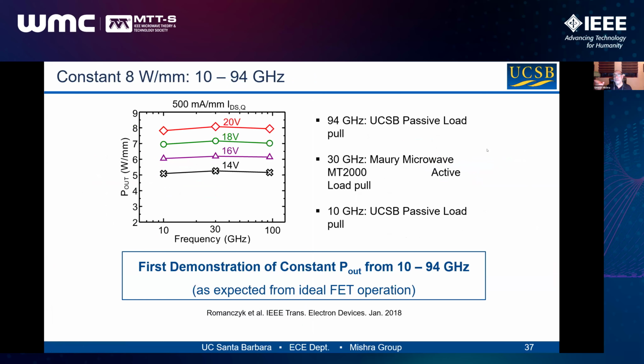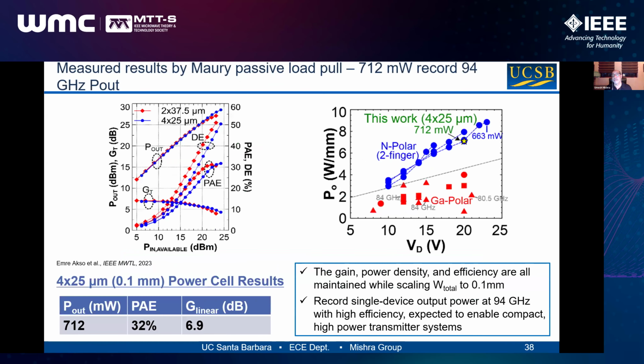And what's good at 94 is also good at lower frequencies. So here you can see we measured 94 gigahertz at the UCSB passive load pull system. We got 8 watts per millimeter. The same device we took to Maury Microwave, and we measured it at 30 gigahertz, and we got 8 watts per millimeter. It's unheard of. It's the first demonstration of a single device operating over all frequencies with the same power density. Of course, the efficiency went up as you went to lower frequencies.